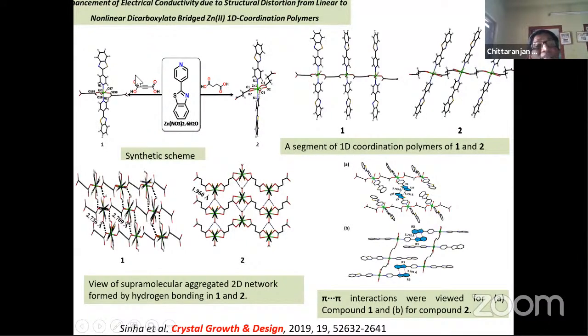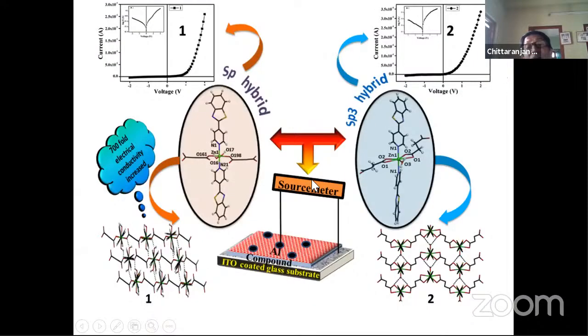Herein we are using this acetylene dicarboxylate derivative, hence acetylene dicarboxylic acid and the succinic acid. The difference is that acetylene dicarboxylic acid is structurally linear. Besides, it is conjugated. It can participate in the charge transportation process, so this is a linear charge transportation process, while the succinic acid is a non-linear type, but charge transportation can be carried out through space. So through space and through bond, both are possible for the acetylene dicarboxylate derivative, but only through space is feasible for the succinic acid. So these two molecules having the two geometries have different conductivity. And this conductivity difference is because of their structure as well as their bridging group behavior.